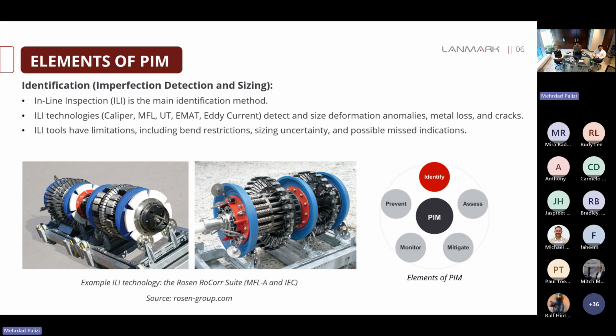MFLA depth sizing is generally about 10 to 15% of the wall thickness. IEC depth sizing is about 1.3 millimeter. Both technologies have a probability of detection of 80%.